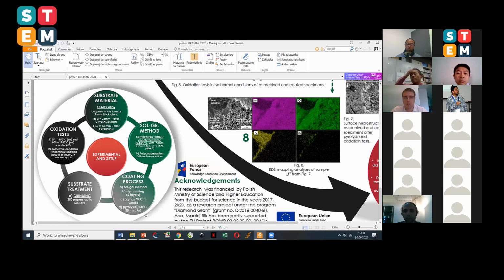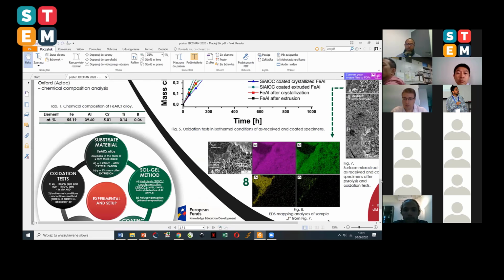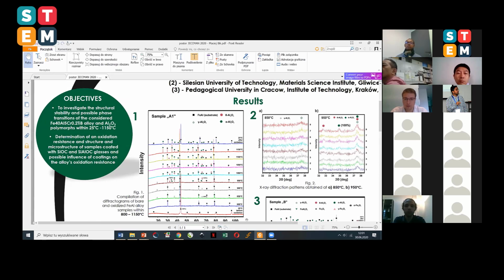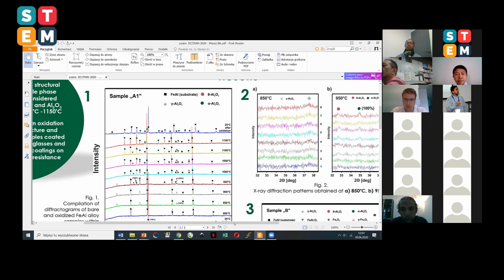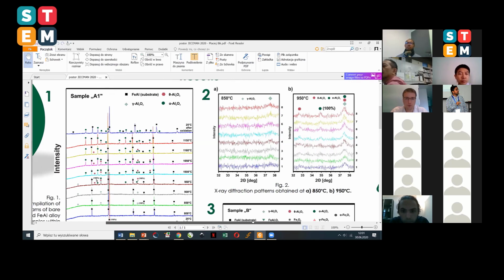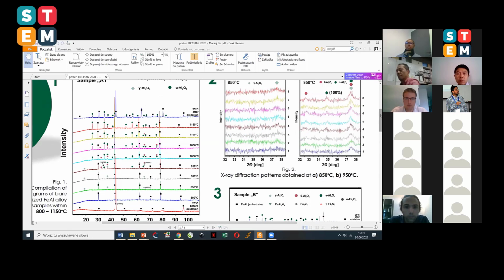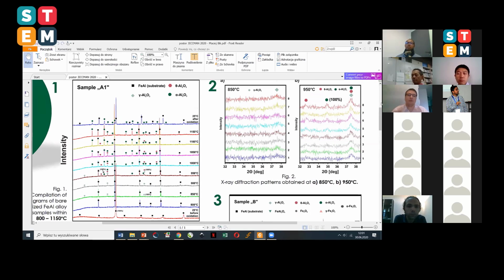After that, coatings were oxidized for 1,000 hours at 1,000 Celsius degrees in laboratory air. So please let me show the first results concerning the in situ XRD investigations in the high temperature range. So I would like to focus on graphs number 1 and number 2, which depict on the left the temperature dependent process, and on the right, in the second figure, the time dependent process.